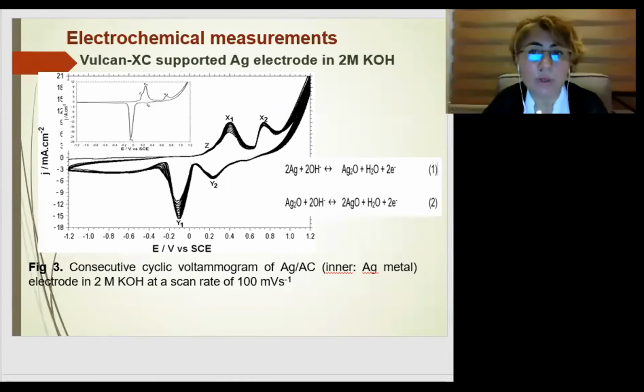Typical cyclic voltammograms for the first and second oxidation-reduction cycles are shown in figure 3, for the Vulcan XC supported silver electrode and for the silver bulk electrode, respectively. The characteristic anodic and cathodic peaks X1 and Y1, and X2 and Y2, correspond to the formation and reduction of the silver(I) oxide and silver(II) oxide phases according to reactions 1 and 2.